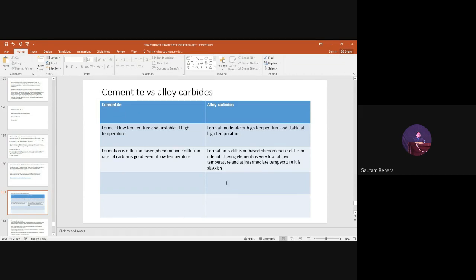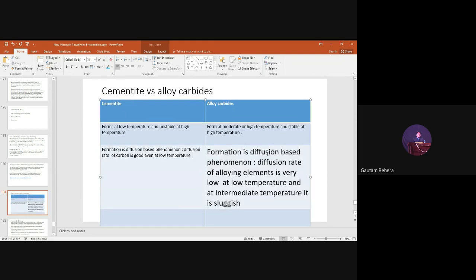So the thing is what? There is a very interesting thing here. You can just look at this one. Just read this one. This is very interesting. Formation is a diffusion based phenomenon. So these precipitates which form in the matrix of the steel are formed due to a diffusion mechanism. If diffusion is happening, precipitates will form, right? Formation is a diffusion based phenomenon, and the diffusion rate of alloying elements is very low at low temperature, and at intermediate temperature it is sluggish. Sluggish means very slow.